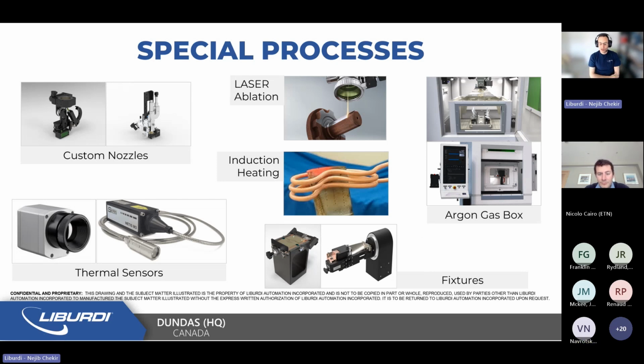Okay. But you can see as well the low pressure turbine case. And as I was saying, you could add all the degrees of freedom to be able to tilt this blade and be able to work on other surfaces of interest if needed. Typically, these, as I said, are custom designed by our mechanical group. And we have to focus as well on the shielding, typically around the areas of interest. Whenever we can, if we can focus only on local shielding, then we can design custom trail cups in order to minimize the downtime that you would have to purge the area of interest with inert gas.